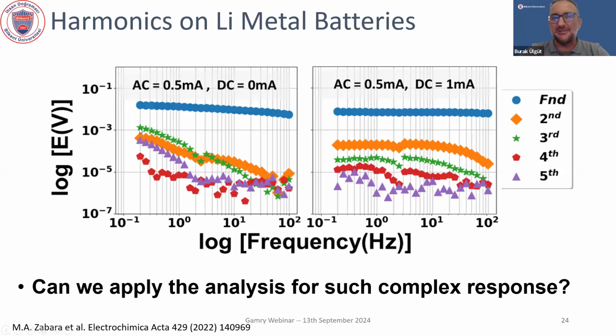So at low frequencies, you can see the third is above the second. And as we go to high frequency, we are getting second above the third. And under this condition, under a DC of 1 milliamp, we always have second above the third. It turns out that when the harmonics are ordered like this, 2, 3, 4, 5, that's an indication of drift. And when you have 3 higher than 2, that's an indication of nonlinearity. So under this condition, our only issue is the battery voltage drifting.